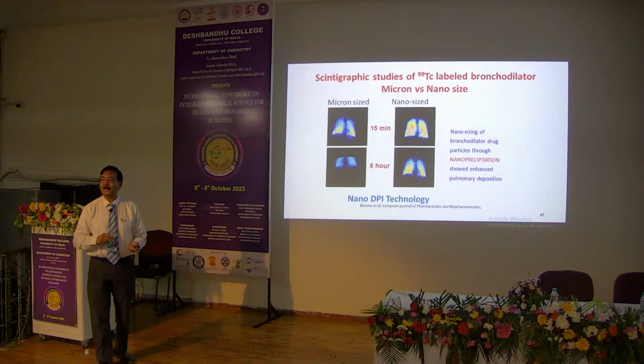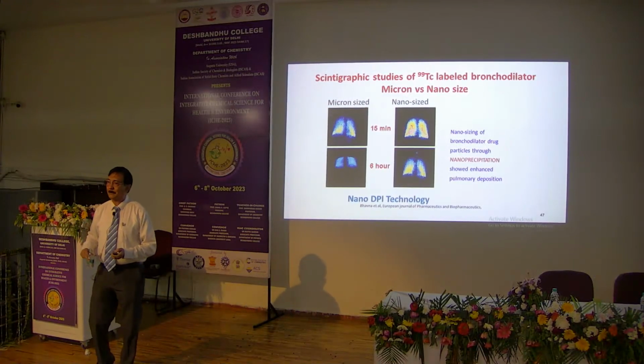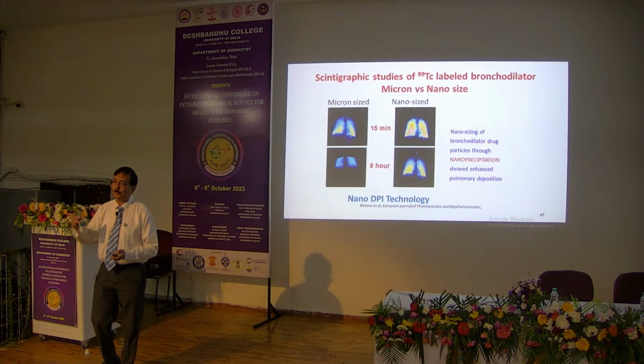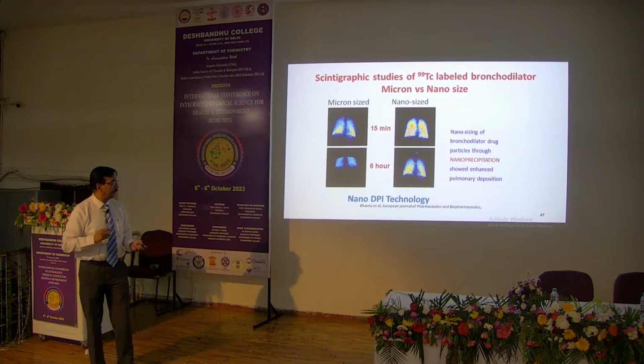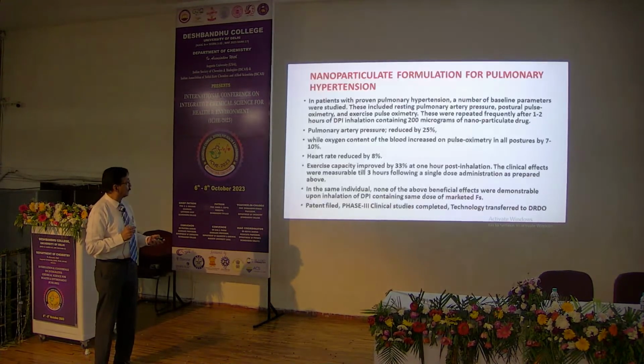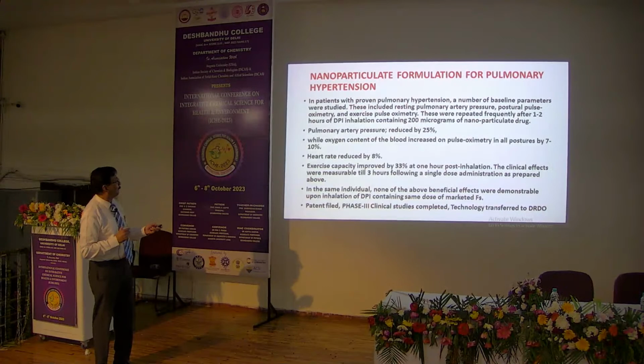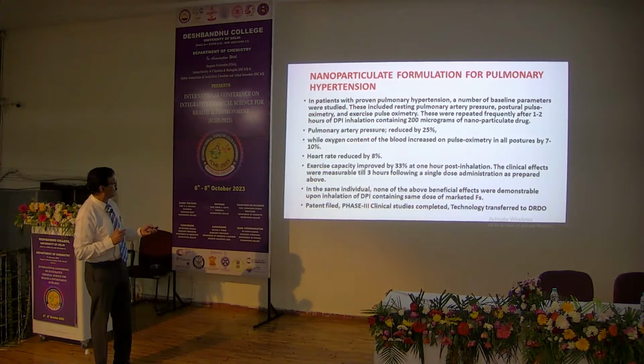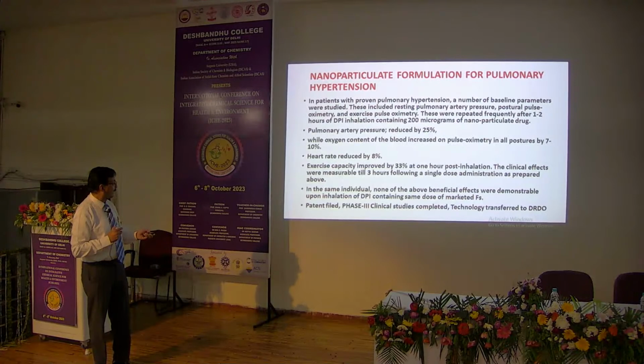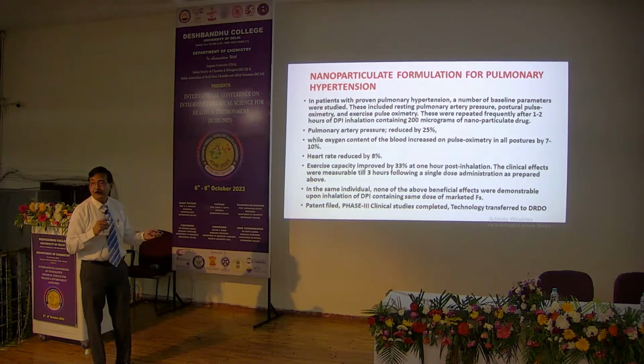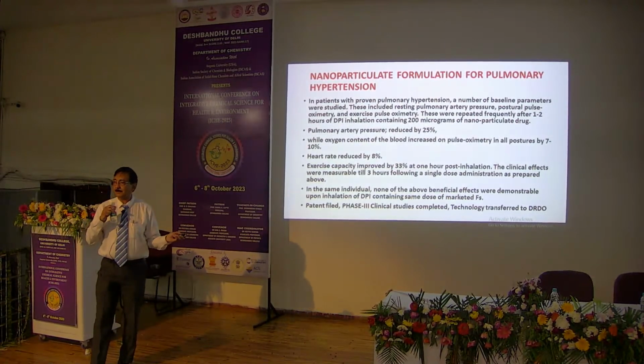So we developed DPIs. You can keep them in the pocket. Even at high altitude, you can just take a single puff. And what we found, when taking a single puff in patients with proven pulmonary hypertension, is that the pulmonary artery pressure is reduced by 25%, oxygen content is increased by 10%, heart rate is reduced by 8%, and exercise capacity is increased by 33%. So this can save their lives.